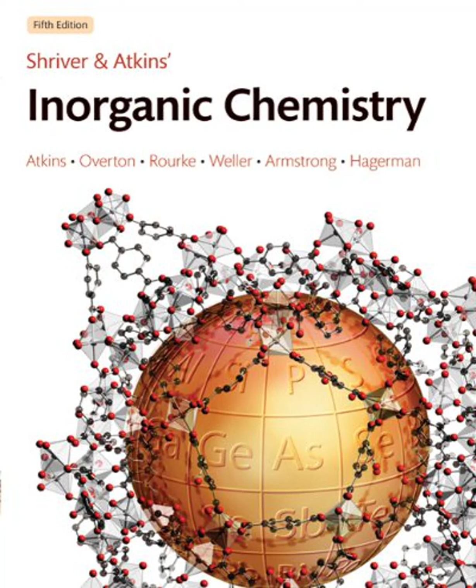Right. Solid C60 itself is just spheres packed together, interacting weakly. But when you intercalate alkali metals into the structure, making compounds like K3C60, things change dramatically. They become superconducting. How does adding potassium make C60 superconduct? It's fascinating. K3C60 becomes superconducting around 18 Kelvin. If you use larger alkali metals like rubidium or cesium, the transition temperature goes even higher.